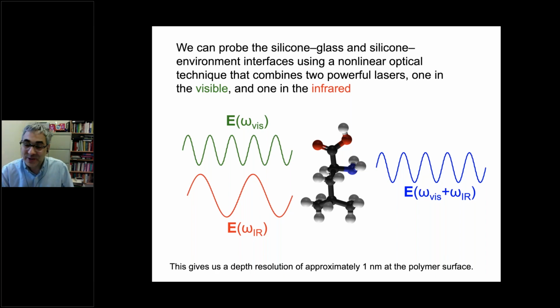So the question is, why do we do this? And the reason we do this is because this gives us a depth resolution of approximately 1 nanometer. And what's so special about this is that only the molecules at the very top of the silicone rubber are able to create this new light in blue that I'm showing you. So it actually doesn't matter how far our beams penetrate into the bulk silicone phase. We can excite, you know, microns or millimeters of material, but the only signal that we get is from the molecules at the very top on a nanometer length scale.